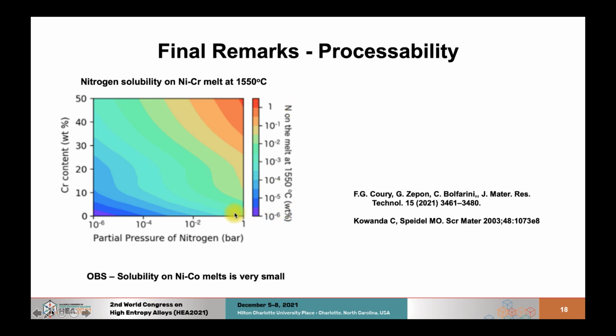So, for example, if we're melting in air or in a poor vacuum atmosphere, an alloy that has more than 30% chrome would be in this region right here. So the melt will incorporate a lot of nitrogen. And nitrogen is very soluble in these alloys, in the FCC phase. It has been shown in the literature. So a lot of these works that are being published that are not reporting the nitrogen content might have different levels of nitrogen, and that could really impact all the properties we've seen today. So one important takeaway, in our opinion, from this is that reporting nitrogen content in these alloys should be very important.